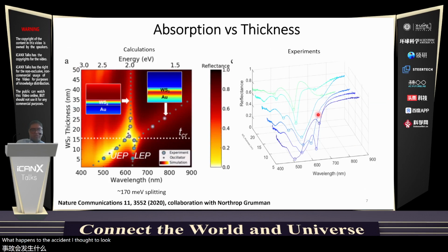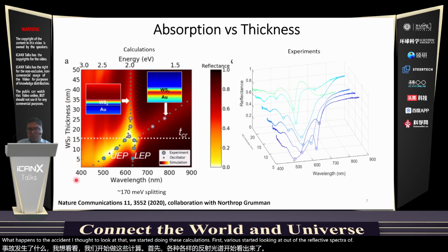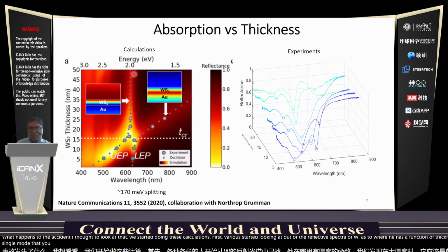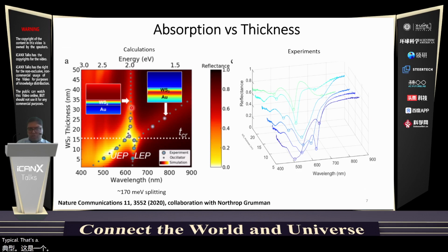And so to look at that, we started doing these calculations first, where we looked at how the reflectance spectra of WS2 vary as a function of thickness. And what we found is that at large thicknesses, you have this single mode that you see, which is the typical exciton resonance at about 2 electron volts. But as you go to smaller thicknesses, at about 15 nanometers or so, this mode splits into two modes, namely the upper exciton polariton and the lower exciton polariton. It actually interacts with this Fabry-Perot-like cavity mode, which has this linear dispersion, as you can see, as a function